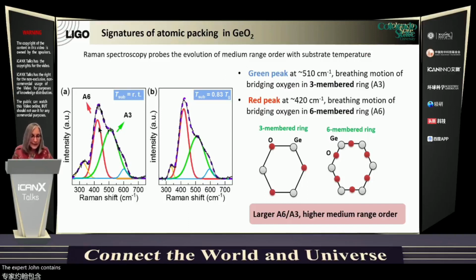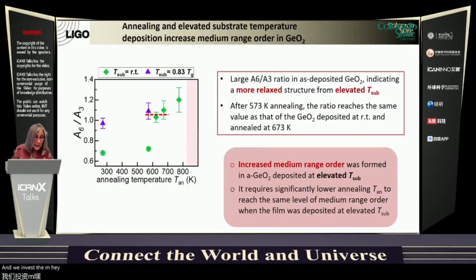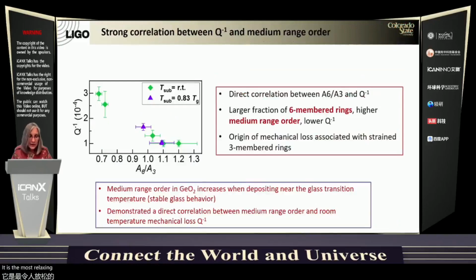The spectrum contains 2 peaks: the red peak corresponds to 6-member rings, and the green peak corresponds to 3-member rings as shown here. 6-member rings are stable in the crystalline structure. So we used the ratio of the areas of these 2 peaks as a measure of the changes in medium range order. Here I plot the ratio of the areas of the 6-member ring to 3-member ring as a function of annealing temperature for the 2 samples that were deposited at different temperatures. And what you see here is that growing at high temperature indeed gives a much higher degree of ordering, a more relaxed structure.